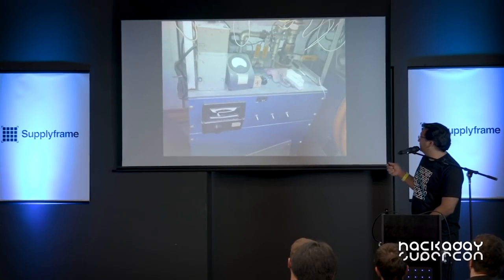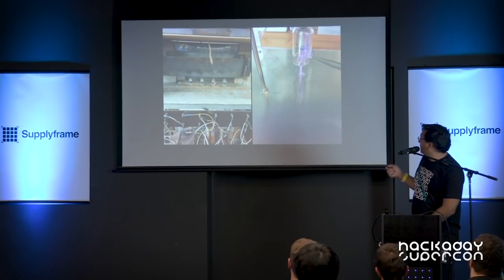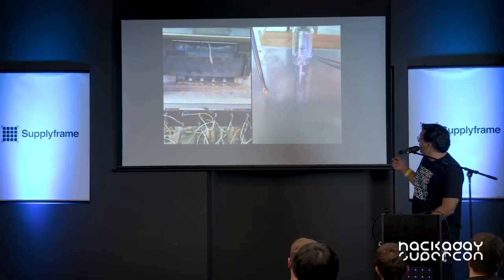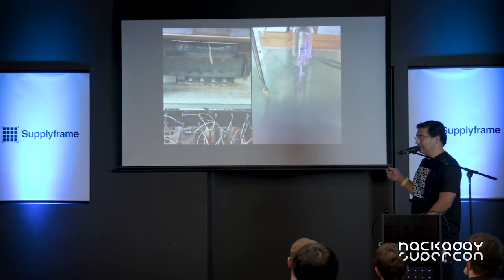Typical valving. This is leak testing. So after you've put your tubes on the pump, you run around with a handheld Tesla coil, and if there happens to be a leak, it will find it, and you'll be able to see the ionization flare behind it telling you you've got a leak, and you've got to throw it away because it's useless now.